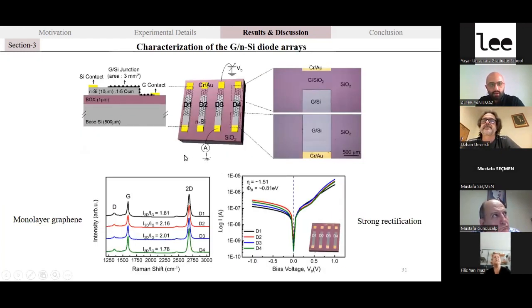After getting the device structure, here you can see the active area of the individual diodes is 3 mm square. Compared with the single pixel, this value is very low, nearly 6 times lower active area. We checked the homogeneity and the success of the device fabrication by using the optical microscope, and then we checked the homogeneity and the number of layers of the graphene by using Raman spectroscopy.